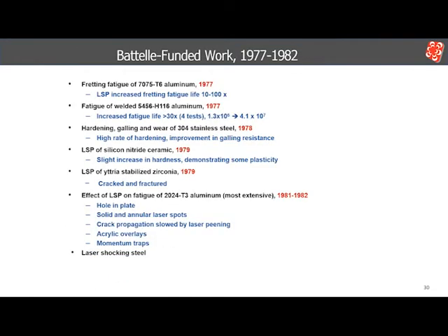In 1977, when it was becoming evident that laser shocking could be potentially useful to industry, Battelle funded an effort to expand the exploration of applying laser shocking to other materials and properties. We first examined the effect of laser shocking on fretting fatigue and fatigue of welds, with long life increases for both. The effect of laser peening on galling and wear resistance in stainless steel showed positive results. Ceramics were also investigated. Shocking silicon nitride gave interesting results with some increases in hardness and plasticity.